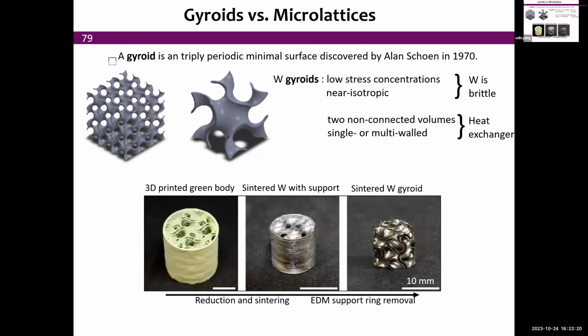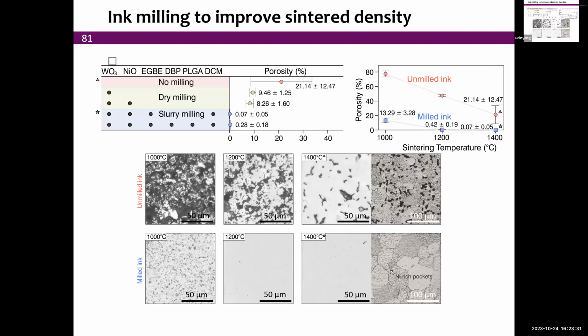So we print with tungsten oxide, which is this kind of greenish shape. It has a support around it. We then sinter, and then we machine the support and end up with those gyroid structures. And relatively going a bit fast, we see that the porosity can go down to near 0%. So we get fully sintered tungsten structures at 1400 degrees C with a little bit of nickel, as we had before. If you don't do things right, if you don't mill correctly, you end up with a lot of residual